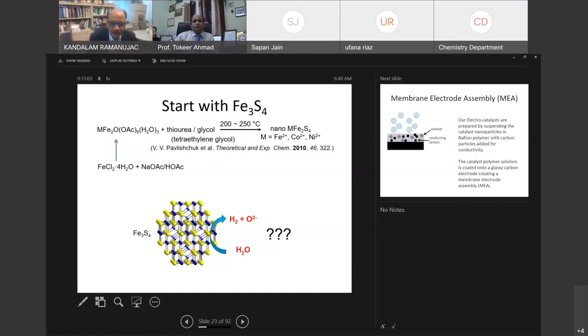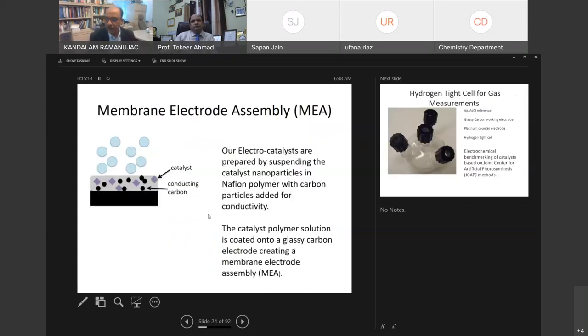And the idea is using these cubane clusters, iron-sulfur clusters here, to see if we can somehow effectively reduce the water to make hydrogen. So this is how we made our membrane assemblies. Because some of the sulfides are not conducting, you need to put in a conducting carbon, and these are all the catalyst particles.